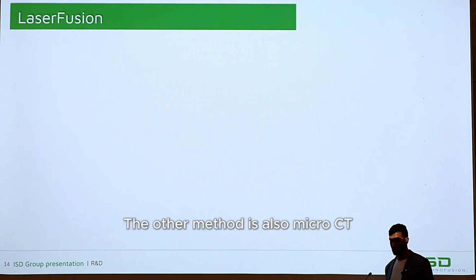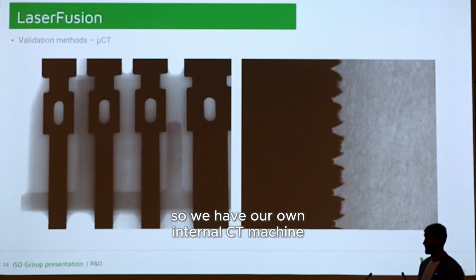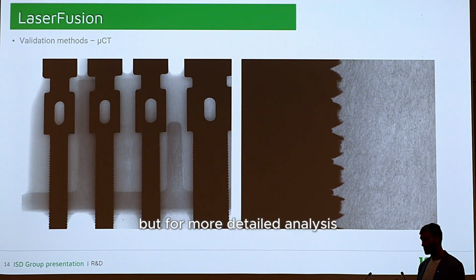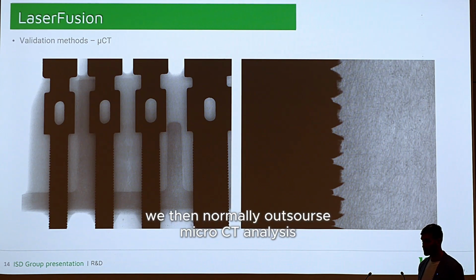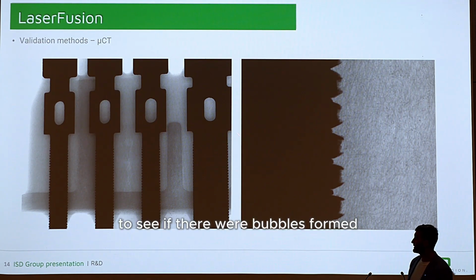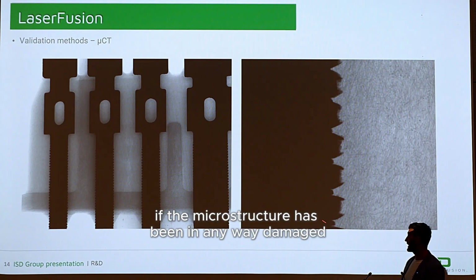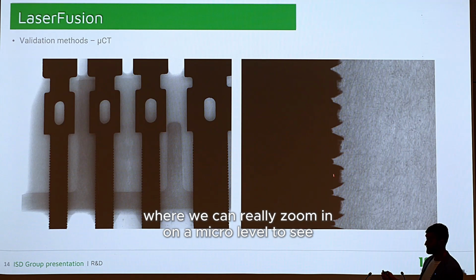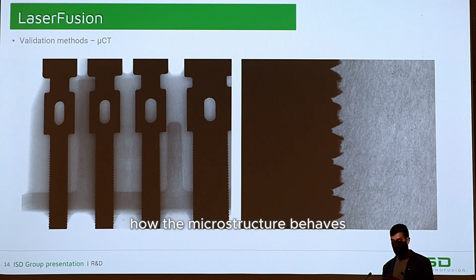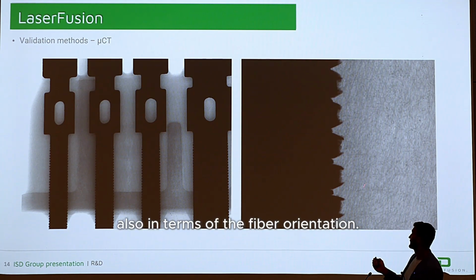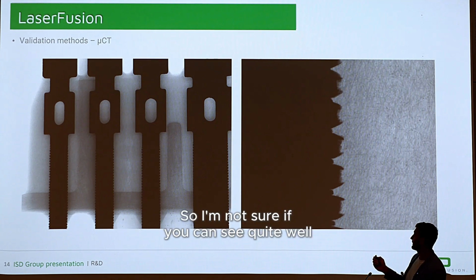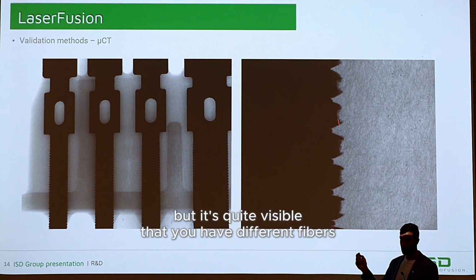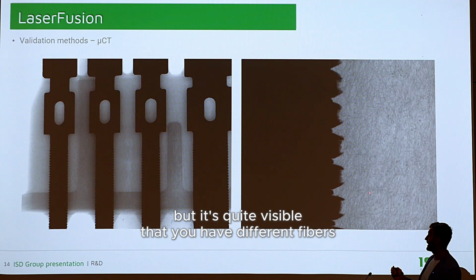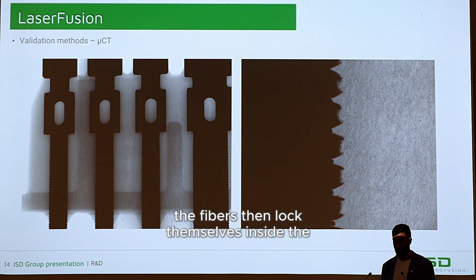The other method is also micro-CT. So we have our own internal CT machine, but for more detailed analysis, we then normally outsource a micro-CT analysis to see if there were bubbles formed, if the microstructure has been in any way damaged locally, where we can really zoom in on a micro level to see how the microstructure behaves also in terms of the fiber orientation. So I'm not sure if you can see quite well, but it's quite visible that you have different fibers. And we also see how the fibers then lock themselves inside the structure.